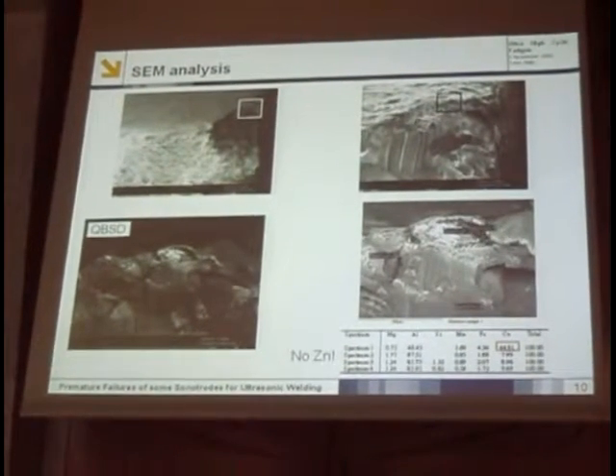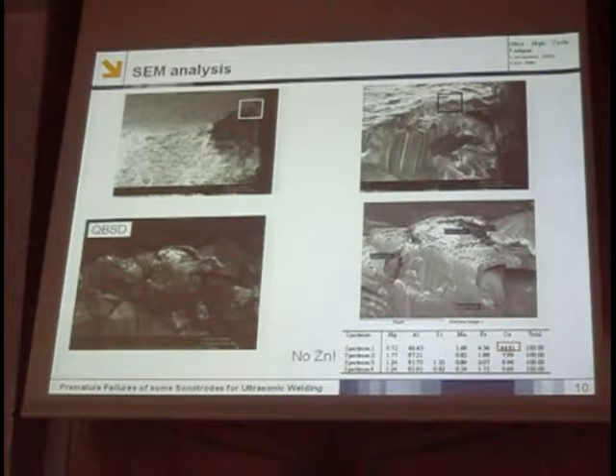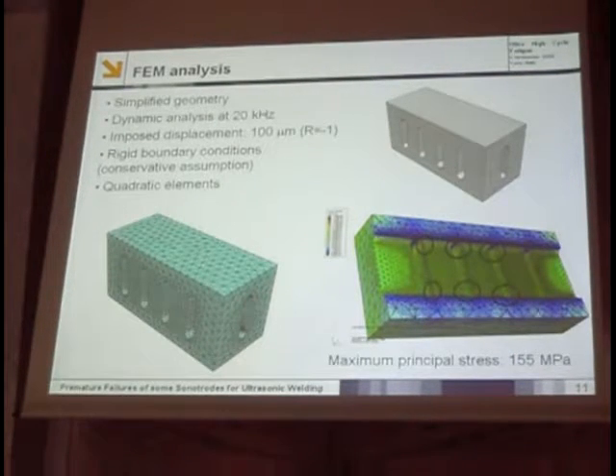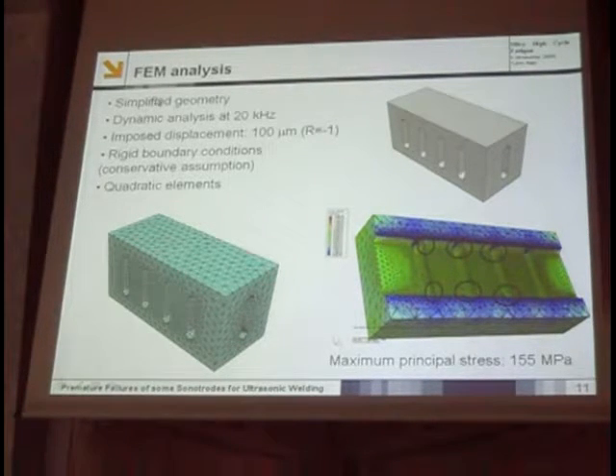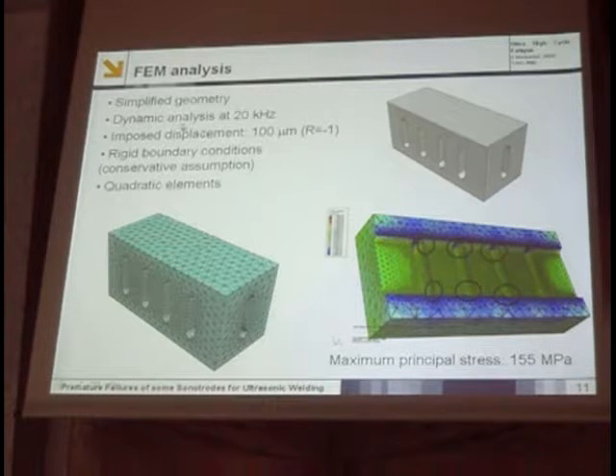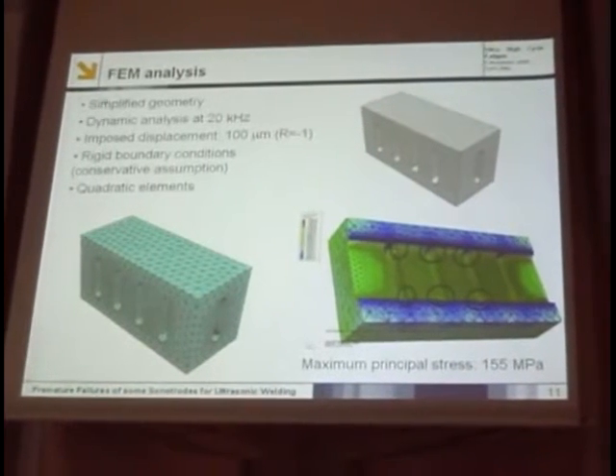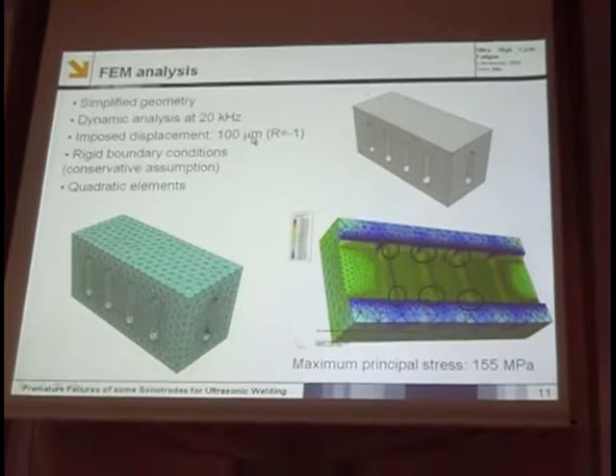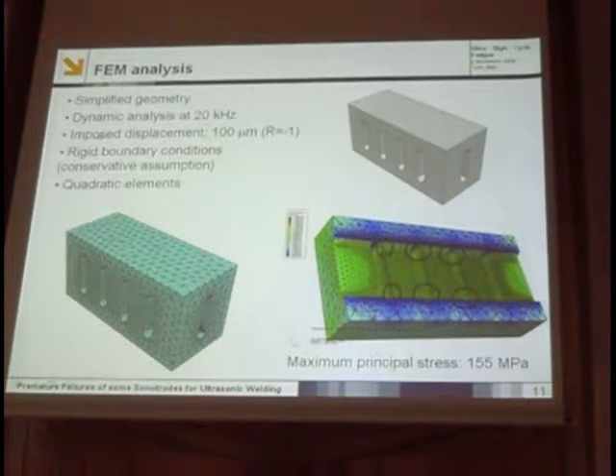But we wanted to go on, and we are still at preliminary results. We carried out some finite element analysis of the sonotrode. I say preliminary because we use some simplified geometry. We have not all the geometrical features of the original sonotrode. We carried out a model of dynamic analysis at 20 kilohertz, that is the working frequency for this kind of tools. We impose the maximum possible amplitude in this dynamic analysis.